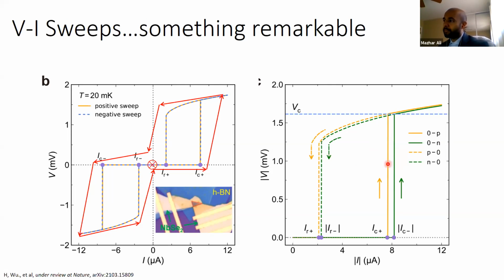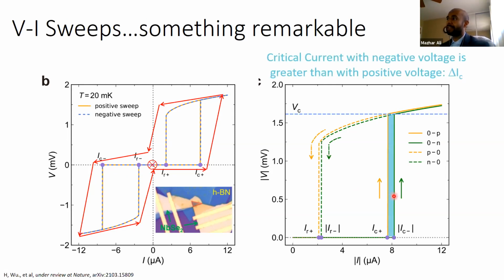What's very important is that the yellow line and the green line, as in IC plus and the absolute value of IC minus, so IC plus, the critical current to break superconductivity in the positive direction, and the critical current to break superconductivity in the negative direction, are clearly not the same. There's a pretty reasonable size gap. There's a delta IC between these two. And the critical current with negative voltage is greater than the critical current with positive voltage. So that's really something that was very clear.